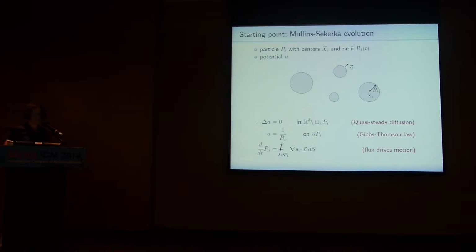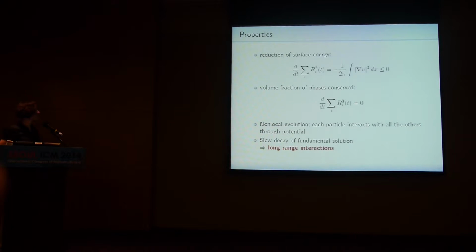But then there's another singularity, which is more serious, that is, even though particles do not move around in space, if you have 2 particles that are large and grow, they might touch each other. So they come close, and then this is not well defined anymore. Okay, this is a simplified version of the Mullins-Sekerka model that is not valid anymore. But think about it, we are in a dilute regime, so this doesn't happen very often. Let's ignore this, but keep it in mind because it will become important later. So as long as particles don't touch, the evolution is well defined for all times.